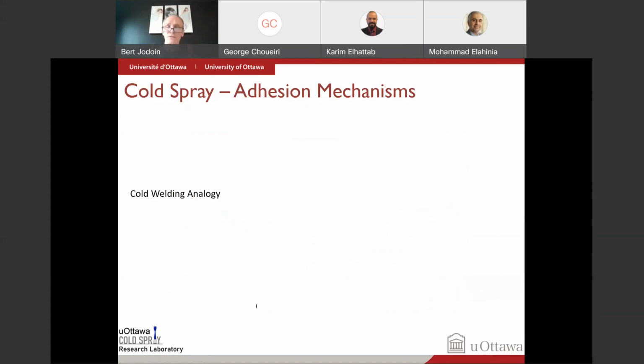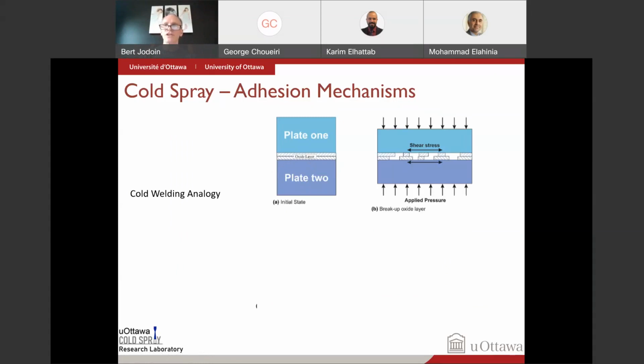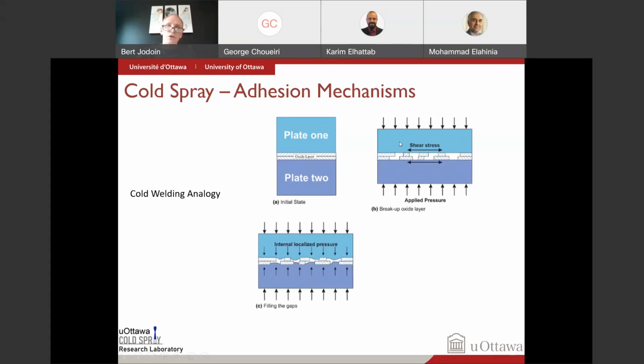Another mechanism, which is sometimes the preferred mechanism, is similar to cold welding. That's why I have the cold welding analogy. When you do cold welding, you have two plates, and of course, any metal will have a native oxide layer. You put the two plates on top of each other, and now you start to apply pressure on them. Of course, you're going to get shear stress, and the two metallic plates can deform, but you have limited deformation available for the oxide, so the oxide layer will break. If you keep applying pressure, then you have cracks that are available for the two materials to flow through. The materials will fill the gap, and eventually you're going to get the two materials fresh, oxide free. If you apply enough pressure, then chemically or metallurgically, you're going to get a bonding. They're going to share electrons, and you're getting just like a regular type of metal where you have metallurgical bonding.